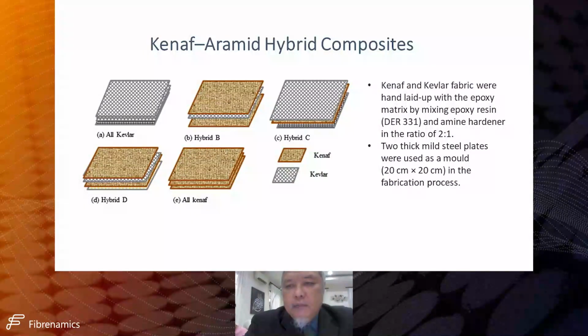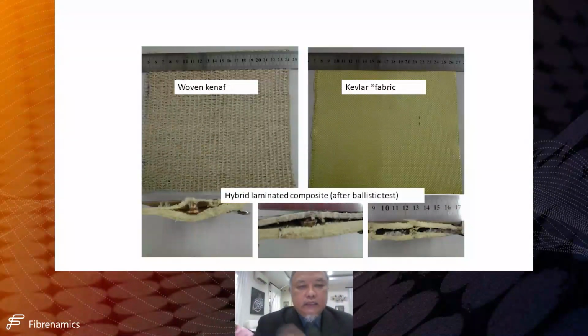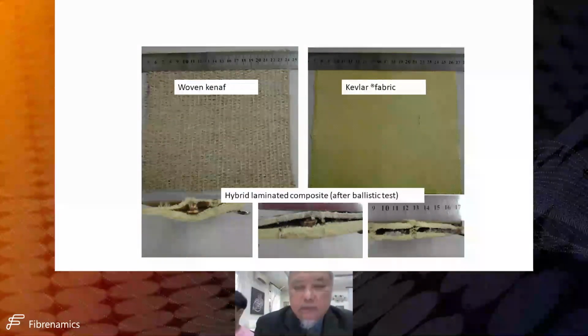Kenaf and Kevlar fabric were hand laid up with the epoxy matrix by mixing epoxy and amine hardener in the ratio of 2:1, and two thick mild steel plates were used as the mold. This is quite simple. This is the material that we use, woven kenaf. And woven kenaf, by the way, is not easy to get. Not many companies are producing that. Mainly we can get kenaf in the form of non-woven, and Kevlar on the right hand side. So we try to hybridize them. The photo below shows the hybrid laminated composite after the ballistic test.